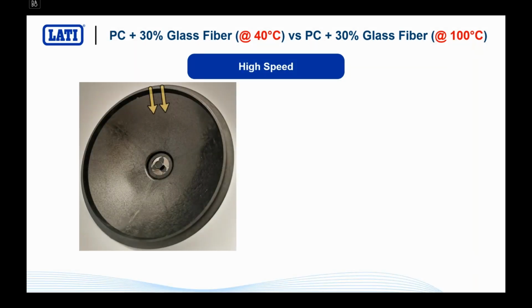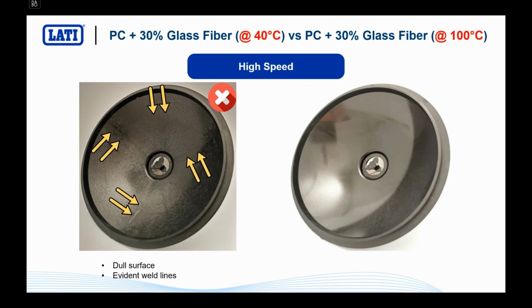With high speed, you always have a poor looking part if you keep the temperature of your tool too low, but the surface finish of your part will be almost perfect if you use high speed and high temperature. I strongly recommend to keep high temperature when it comes to amorphous plastics, even semi-crystalline plastics, but amorphous are extremely sensitive to the tool temperature, because if you keep a low temperature of your tool with polycarbonate, you will promote the impact resistance of plastic, but you can somehow mold some stresses in. It's something that should be avoided. Always rely on the instructions that you can see on our technical data sheet.